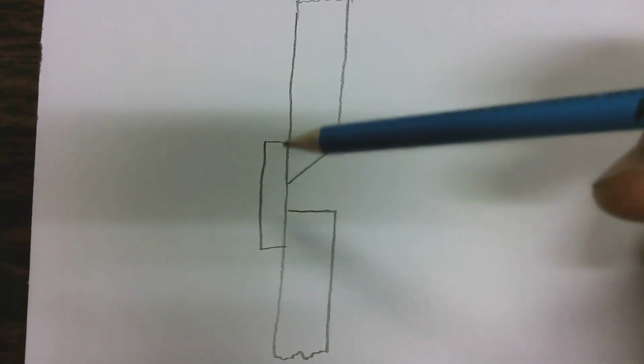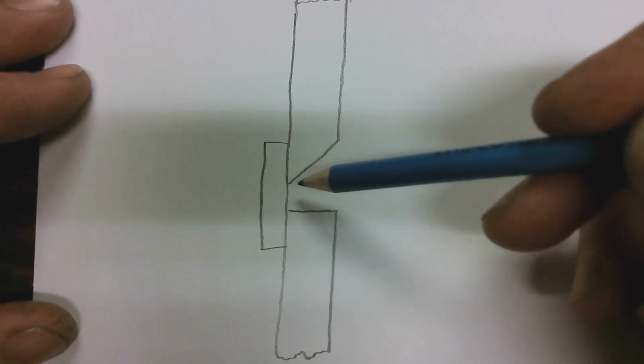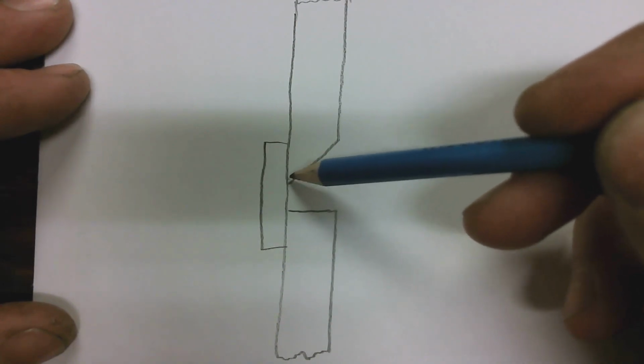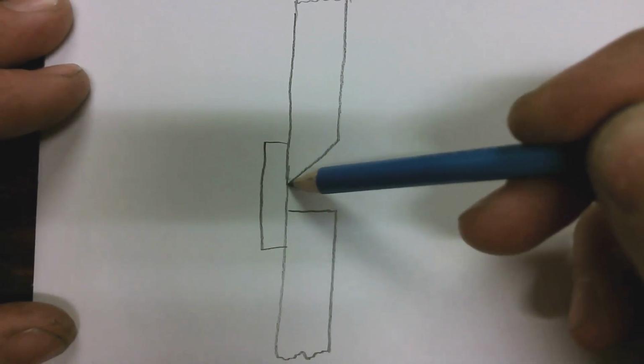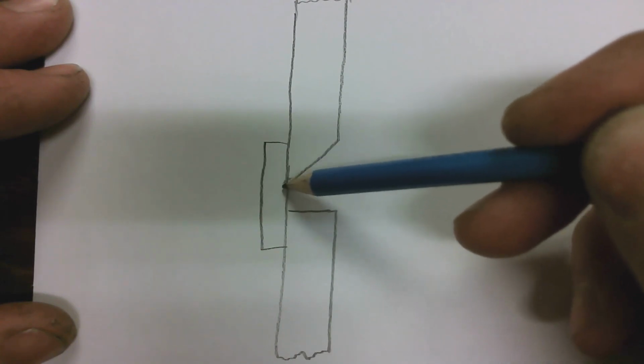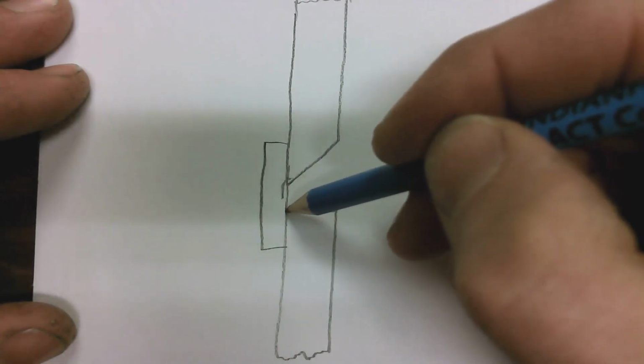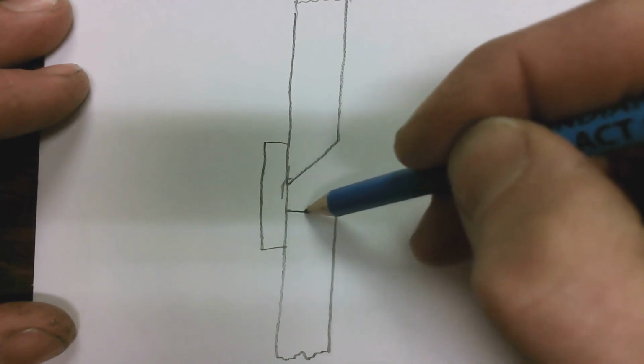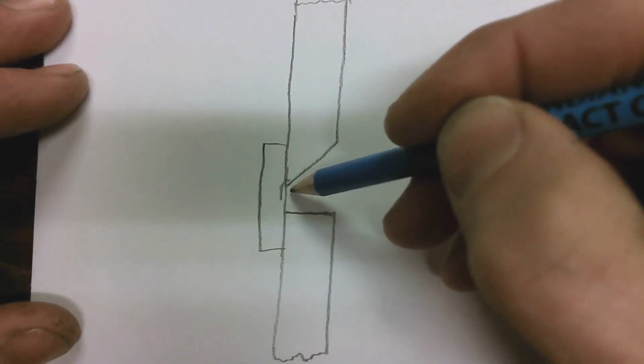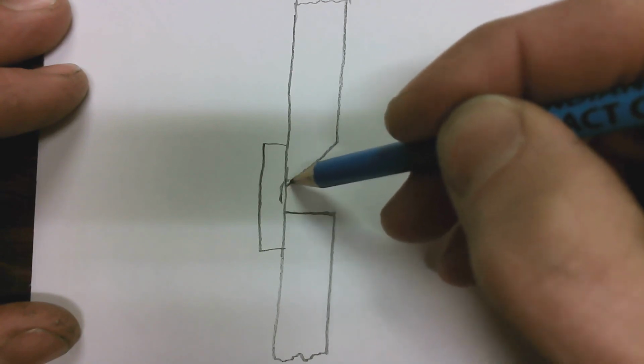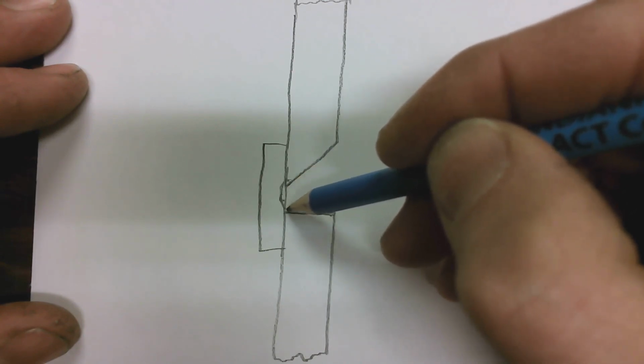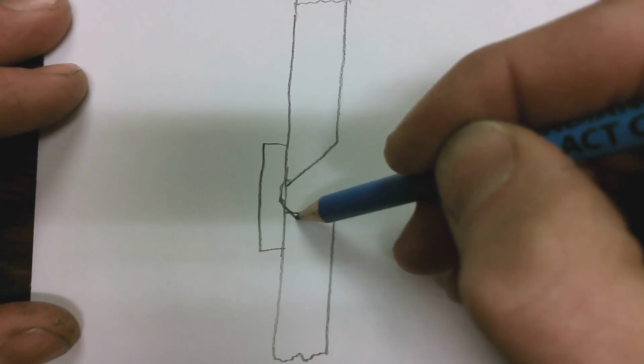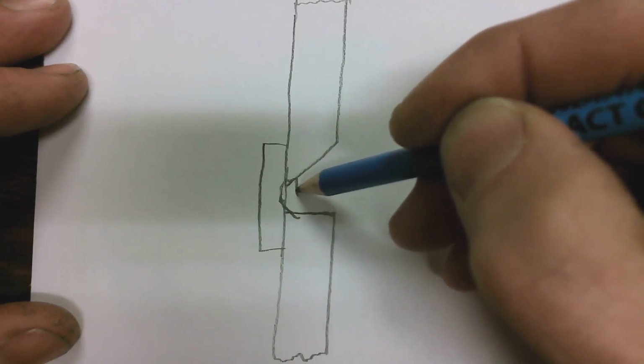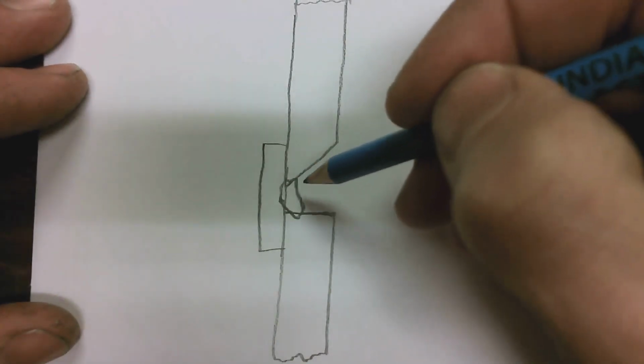All right, and what happened on that particular fail was the weld was tying in very nice to this sharp corner because it is a thin edge, and the student tied in pretty well to the backing strip. But this thick piece of metal, okay, and gravity causing the liquid metal to kind of fall down created something like this. Okay, so we got a weld bead that looks something maybe like this on their root pass,